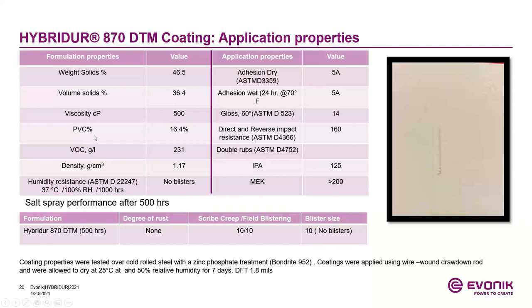We did the humidity resistance. This is the Cleveland humidity test, ASTM D2247, for 1,000 hours at 37 degrees, 100% relative humidity. And it passed with no blisters. And we also did a salt spray performance after 500 hours. You can see the picture here. It typically has no rust here.